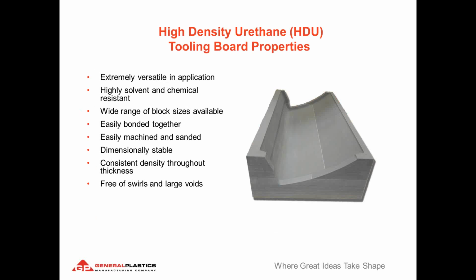So HDU tooling board specifically has extremely versatile applications. Because of the properties in chemistry, there are really an infinite amount of combinations, we can really modify and change properties, toughness versus Tg, thermal resistance, chemical resistance, and so there's really a boundless number of iterations that we can formulate to. So they're also highly solvent and chemical resistant. And that's important when you look at surface sealers that are solvent-borne, paints and coatings, and also even matrix resins for composites. They're resistant to vinyl esters, polyesters, of course epoxies and urethanes don't affect them either.